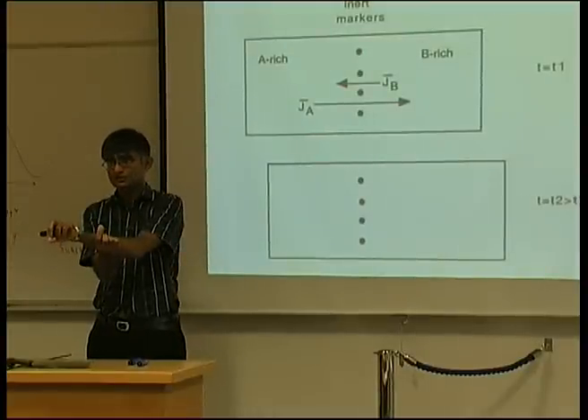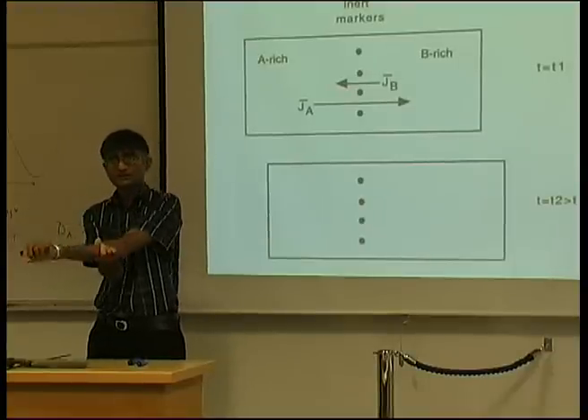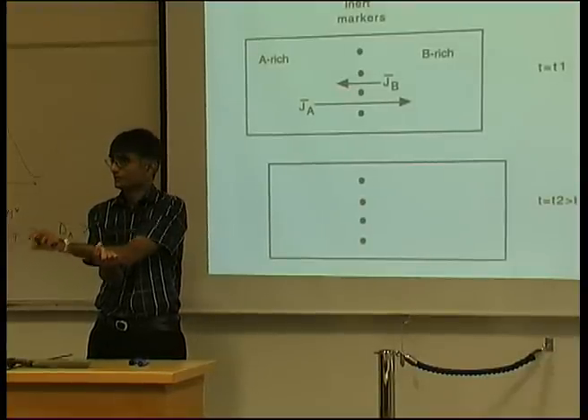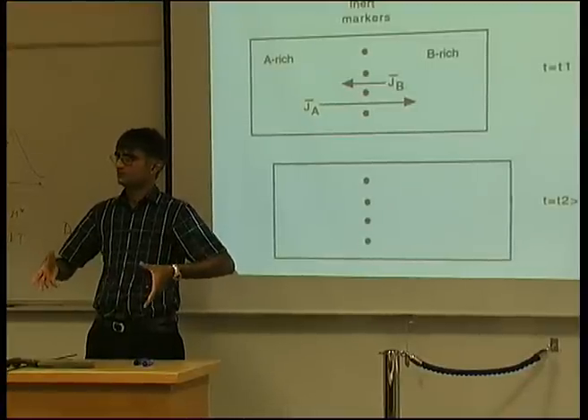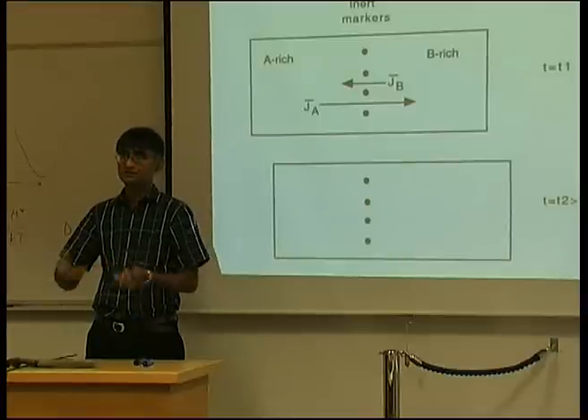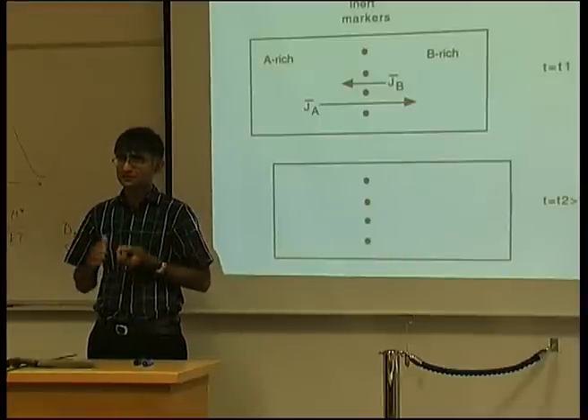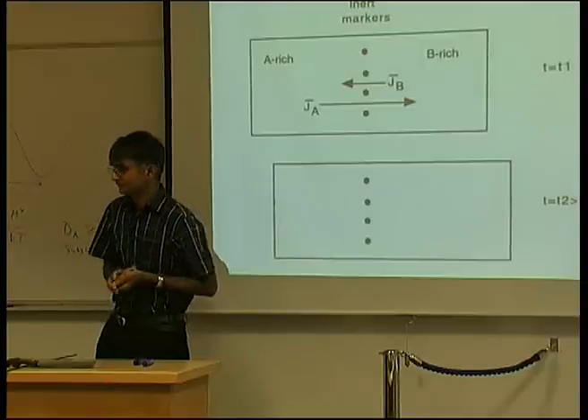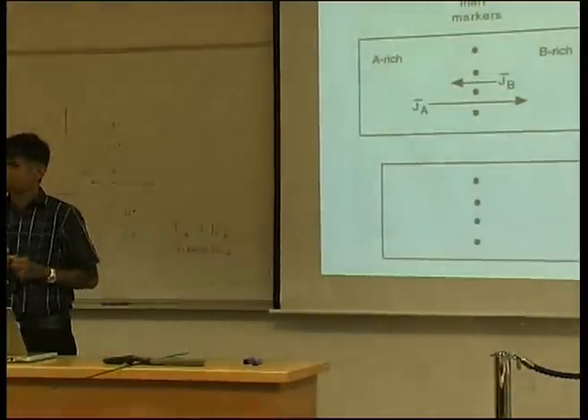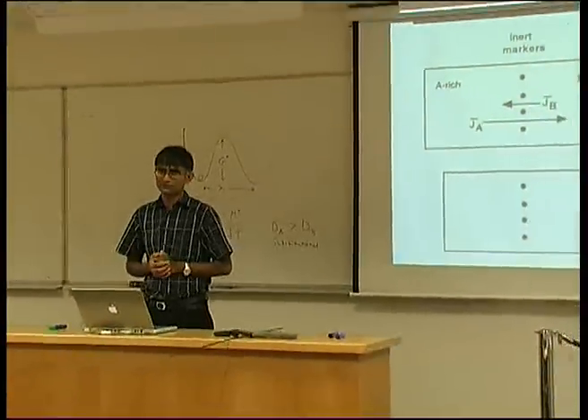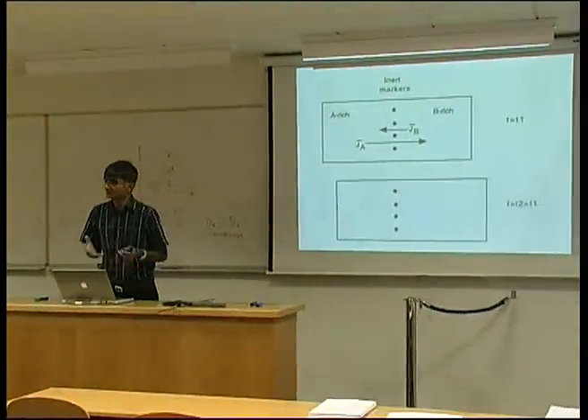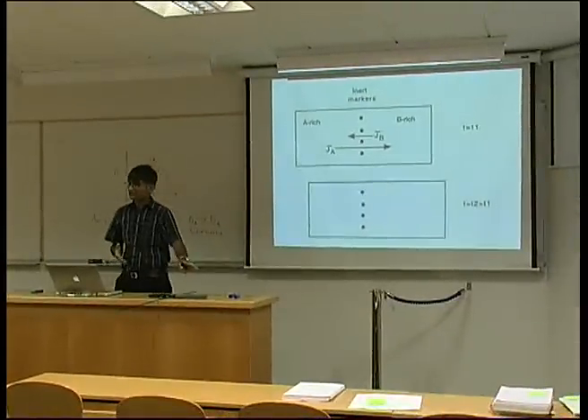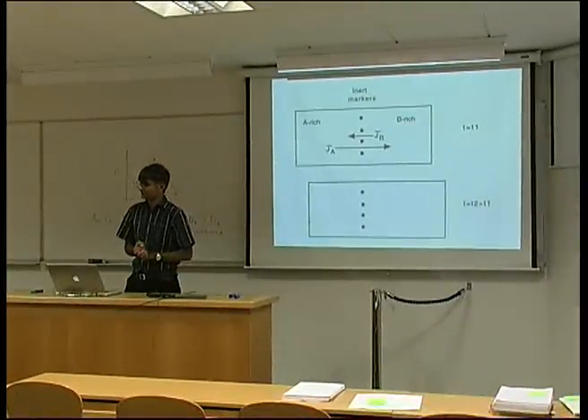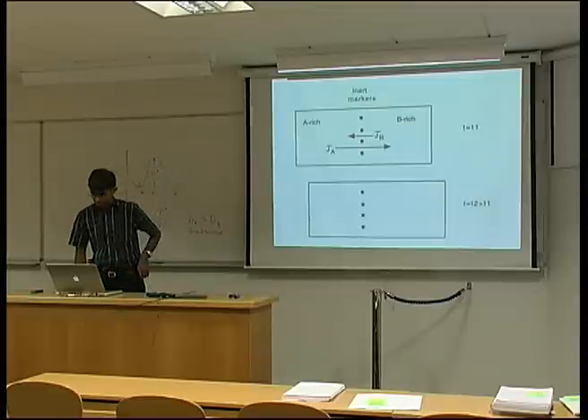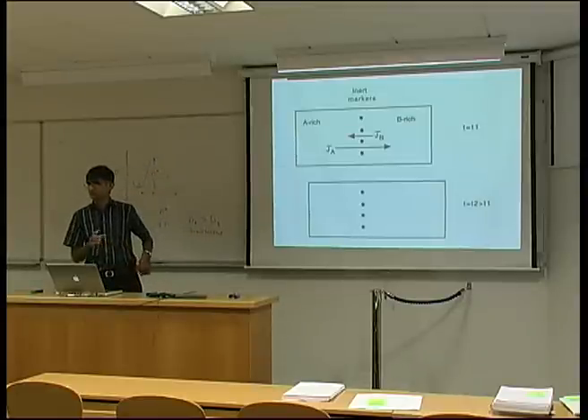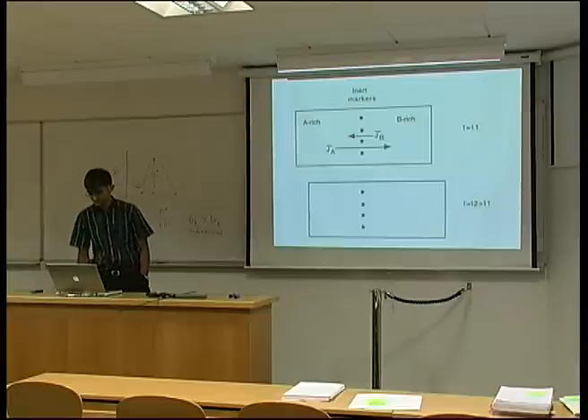If you have a place exchange, then if one atom goes this way, another atom has to go in the opposite direction. So this beautiful, simple experiment conclusively proves that the mechanism of diffusion in the vast majority of cases is by a vacancy mechanism. This is the kind of experiment I would love to do to prove something. It is so simple and there is no ambiguity in the interpretation of the result. You can physically see the specimen move as a function of time. So this is called the Kirkendall experiment, although it was Kirkendall and Smigelskas who actually did the work together.